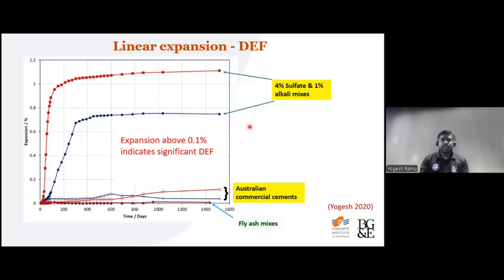Why some cements are expanding and some are not has to do with the chemistry, as I mentioned earlier. Australian commercial cements are not that susceptible to expansive DEF, which is good news for us. And even with the high sulfate and alkali cements, if you replace that with 25 percent of fly ash, you can see we can actually eliminate the expansion even in the worst cement cases. So that's why adding SCMs to mitigate DEF is a practically viable option.